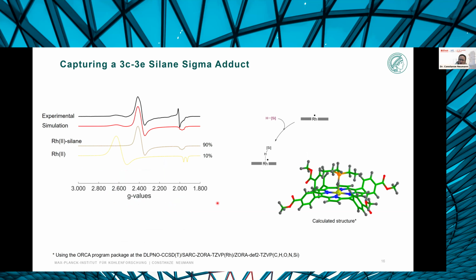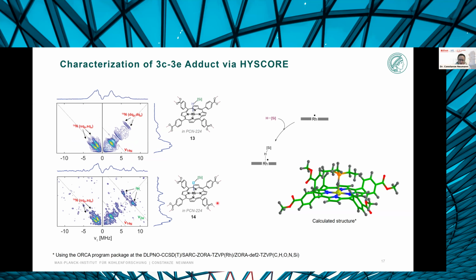And what was nice is that upon addition of the silane, we could see the formation of a 3-center, 3-electron silane sigma adduct, the formation of which we've never observed in solution. And we believe that the reason for that is that in solution, if such an intermediate was formed, it would immediately be split by another rhodium-2 center that approaches the silane adduct and leads to the formation of rhodium hydride and rhodium silyl. Whereas in the MOF framework, such intermediates can actually be stabilized, which is very beneficial to the